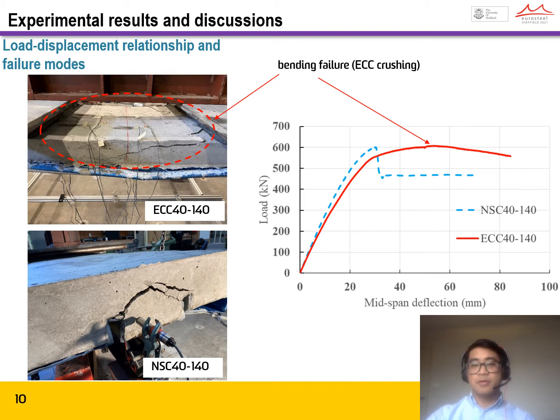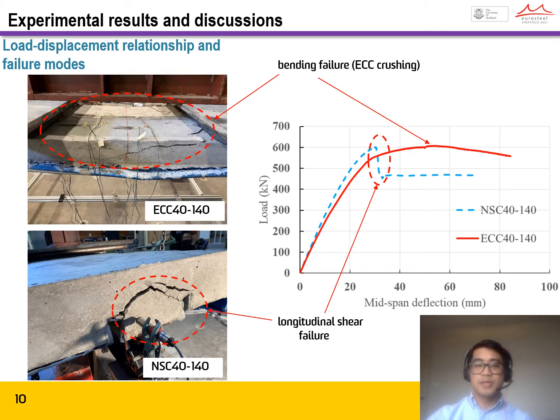The reason for the abrupt failure was that the NSC beam exhibited longitudinal shear failure near the support ends. This is a very common failure in an NSC composite beam utilizing high-strength steel, when the top NSC slab is not reinforced with adequate transverse reinforcement. As the two beams have the same geometrical details and almost similar mechanical properties, it can be demonstrated here that the ECC beam is capable of resisting the longitudinal shear failure over its NSC counterpart.